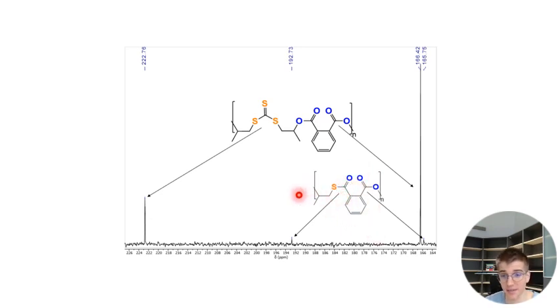So this ester thioester repeat unit that you get just from the copolymerization of the cyclic thioanhydride and the epoxide, right? And you could see this quite clearly because the 13C spectrum really helped us out here, because the ester, thioester, trithiocarbonates, all of these carbonyl resonances spread over 60, 70 ppm, and they come very definitively. So within 2 to 3 ppm, regardless which substitution they have, they can really be used like a fingerprint. And so something that comes around 192, 193 ppm in the carbon spectrum, that's usually a thioester. And it was clear, well, these seem to be errors in this sequence.